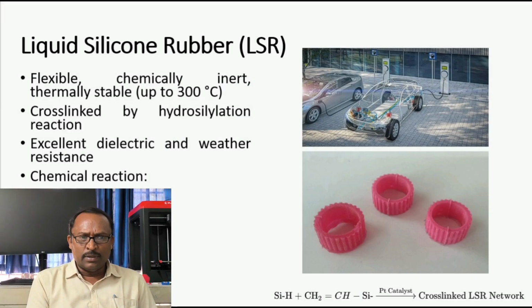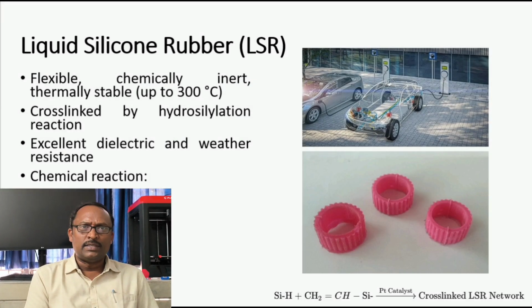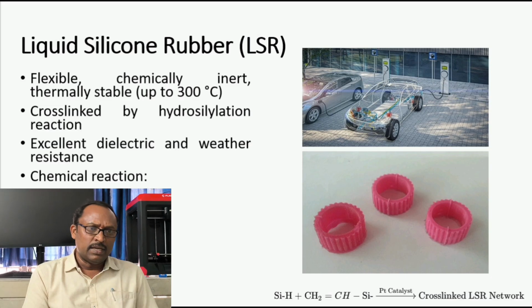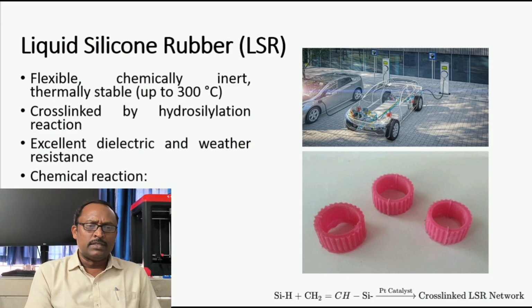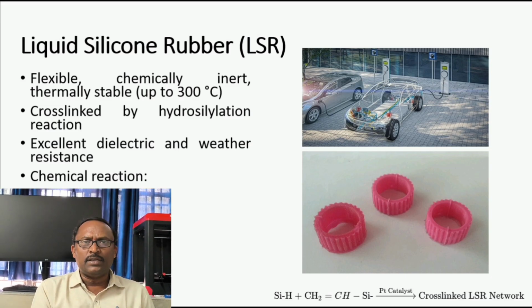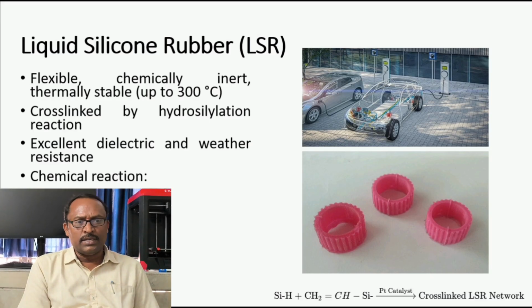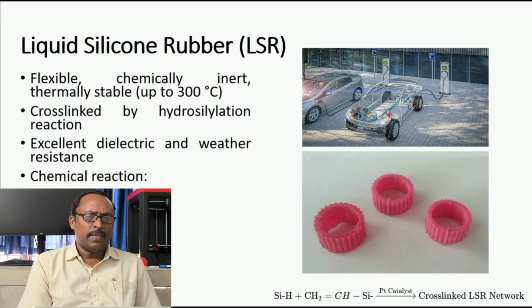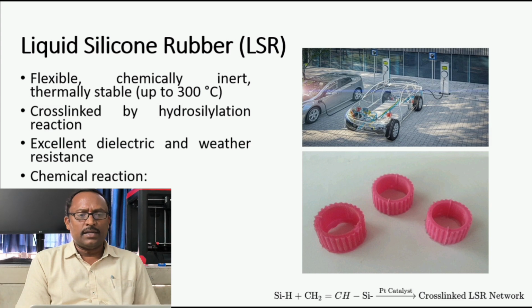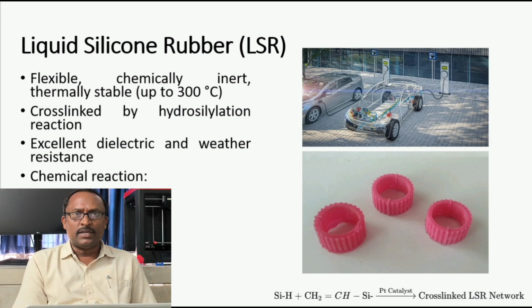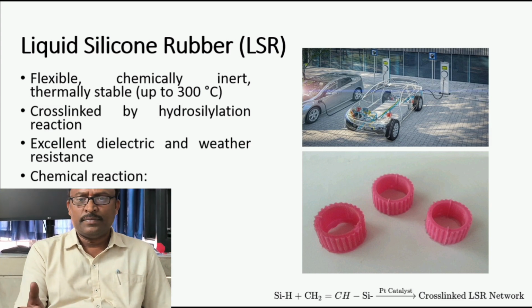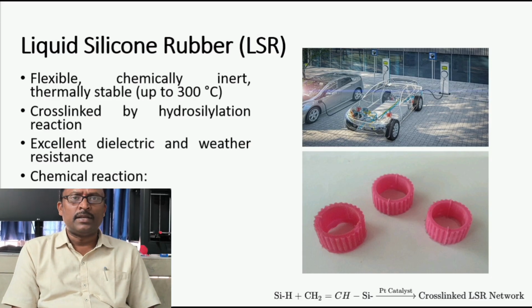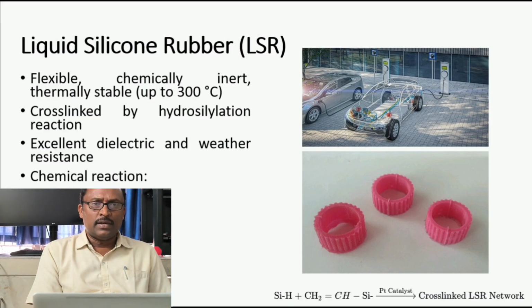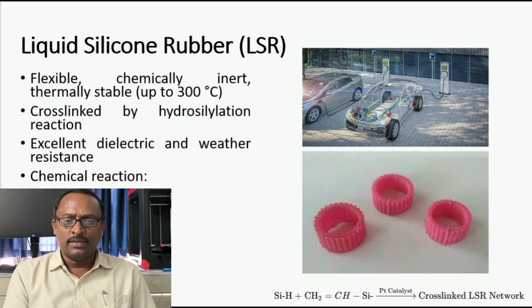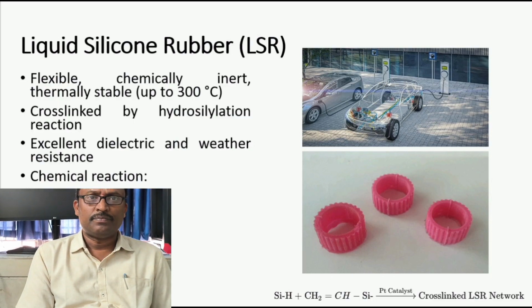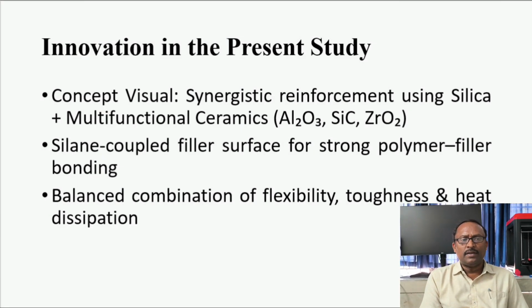Liquid Silicone Rubber is the matrix material which was used, and ceramic fillers are used as reinforcement. Liquid Silicone Rubber is flexible, chemically inert, thermally stable up to 300 degrees centigrade, cross-linked by hydrosilylation, and has excellent dielectric and weather resistance and chemical resistance. And you see in the diagram that the electric vehicle is charged, and the silicon rings are designed by using this material. Innovation in the present study.